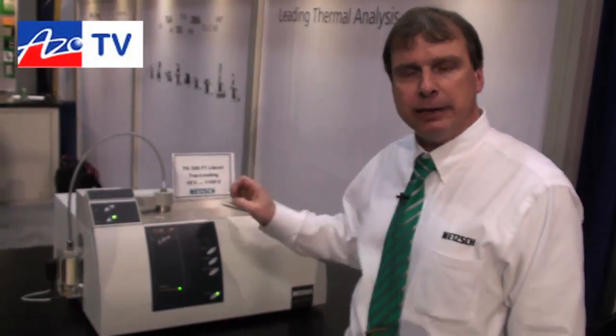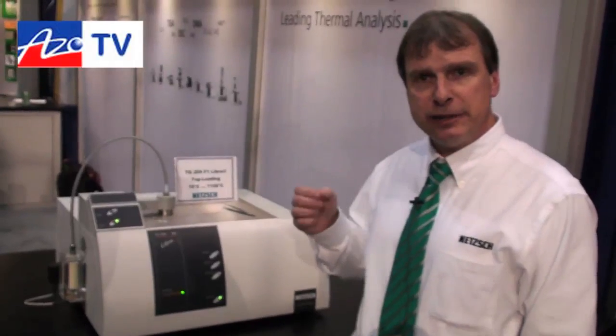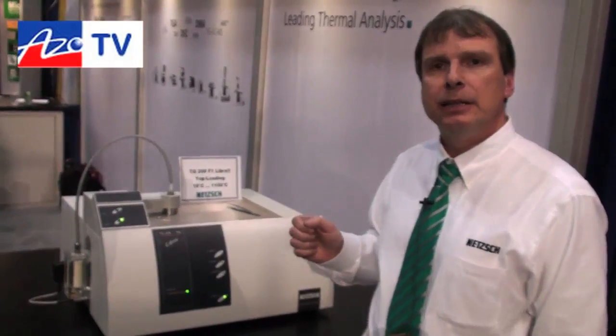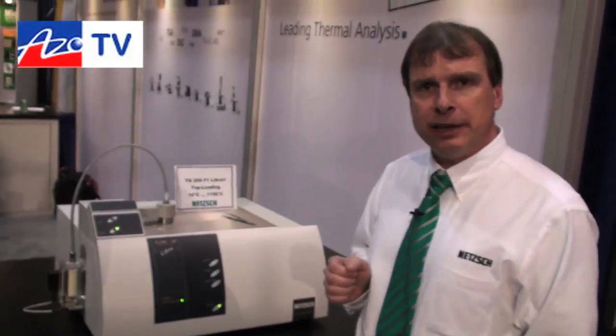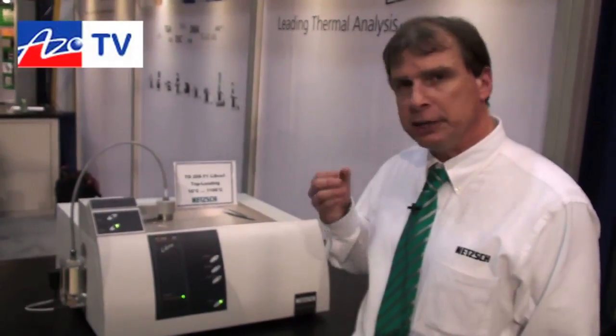Okay. Once this is closed, it's now vacuum tight. So that means if we have an oxygen sensitive material, we could pull vacuum and backfill with inert gas so that you don't get unwanted oxidation during the experiment.